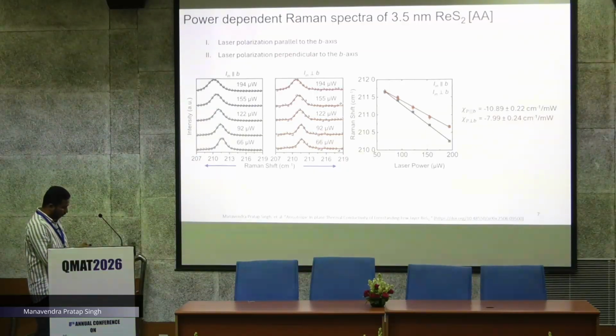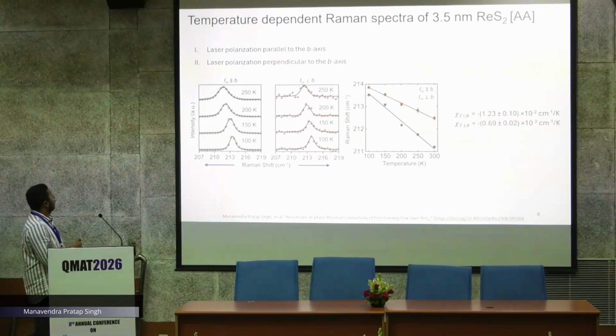We have two scenarios here. In one case, the laser polarization will be parallel to the b axis, and in the other case it will be perpendicular to the b axis. In both cases we have performed the temperature and power dependent measurements and calculated the first order power coefficient, which shows the anisotropic nature because it's different along the different axes. Similarly, we have performed temperature dependent Raman spectra for the same sample, and it also shows anisotropy in its temperature coefficient due to the anisotropic phonon dispersion.